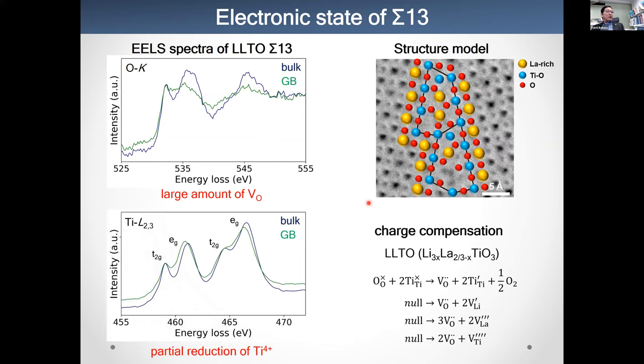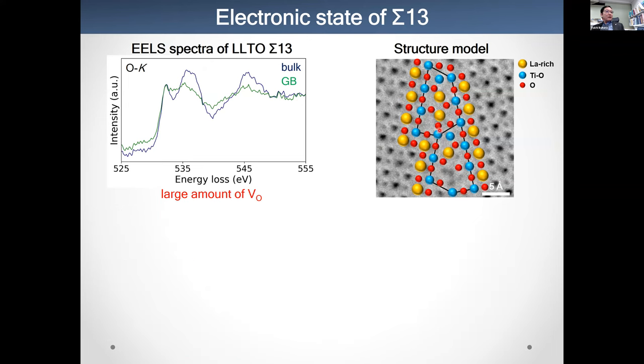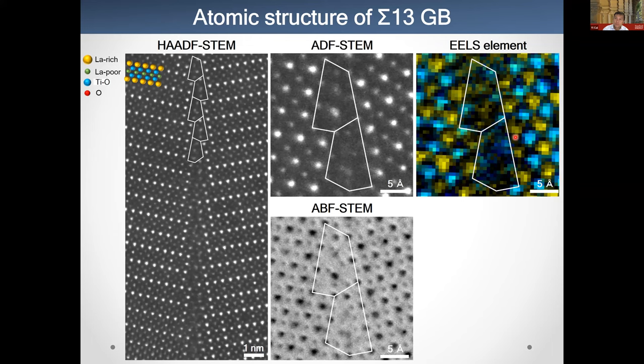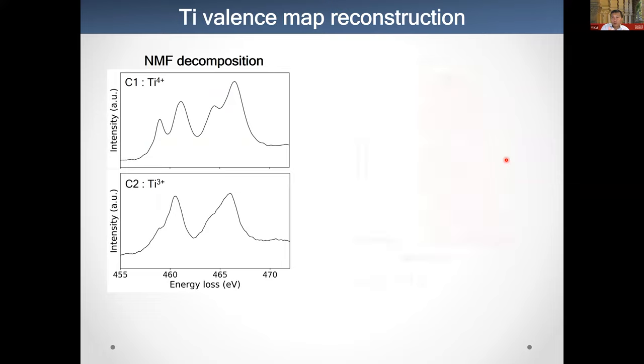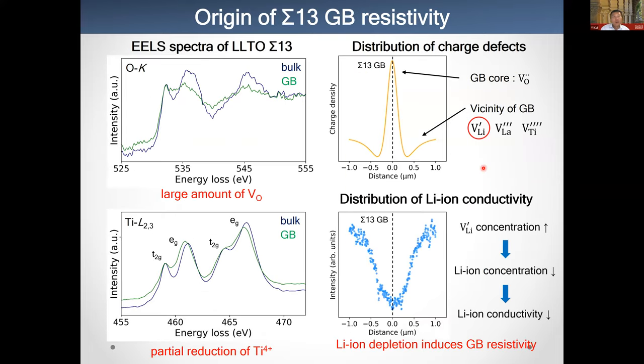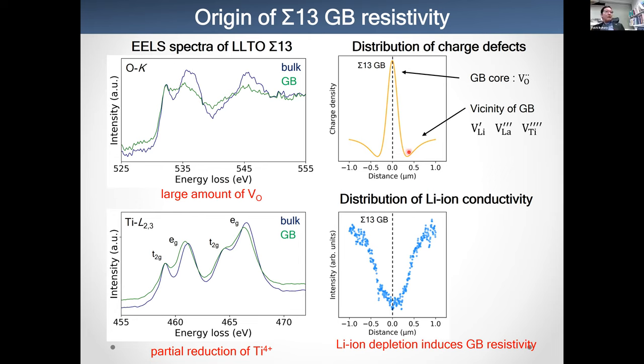I think this is a difficult question. In this case, we just measure the diffusion along grain boundaries. But the question is the diffusion across the grain boundary, right? My question is, in addition to the lithium concentration, because at the grain boundary the bonding is also changing due to oxygen vacancy, is there a possibility that the energy barrier for lithium diffusion is also changing? Yeah. Okay. I think so.